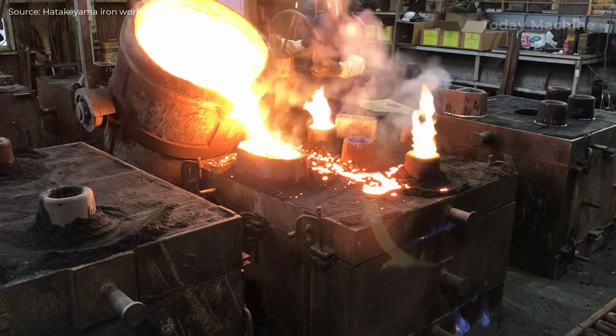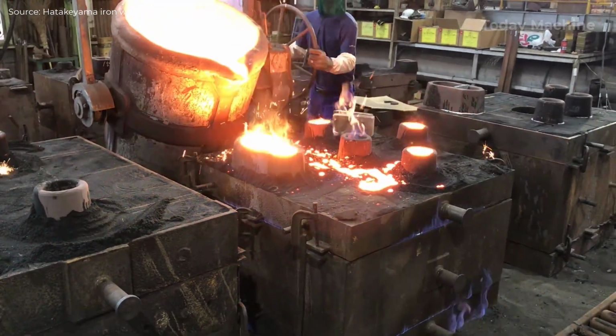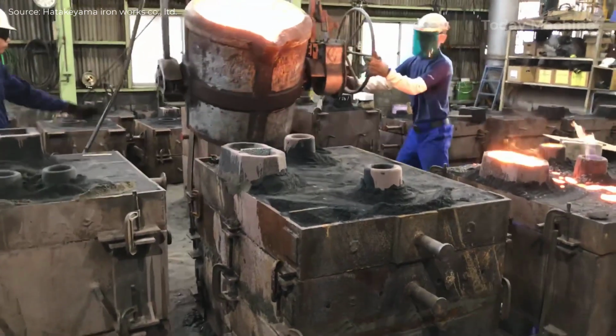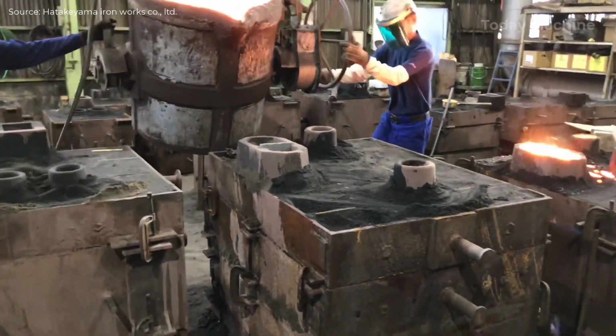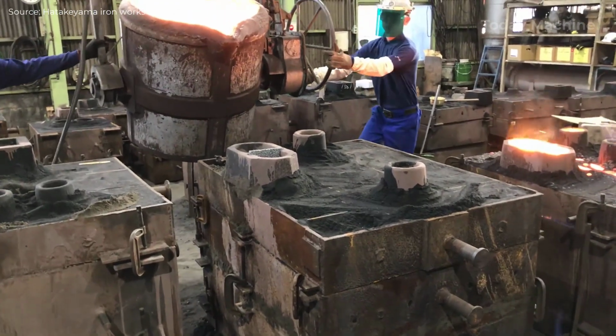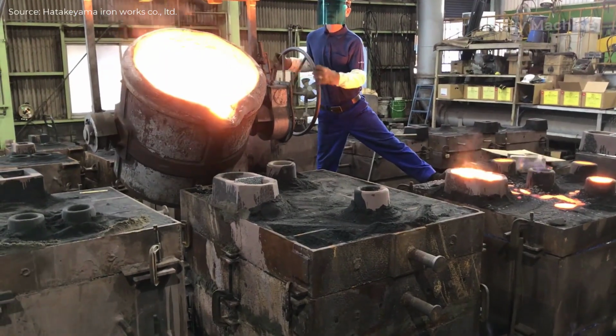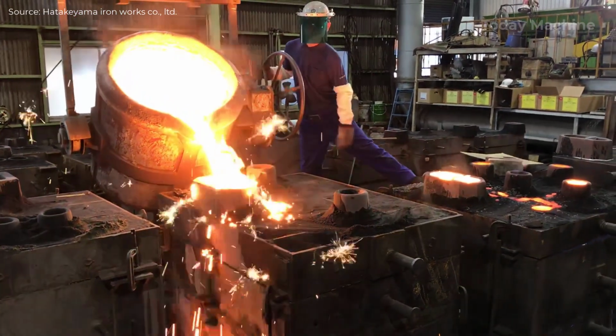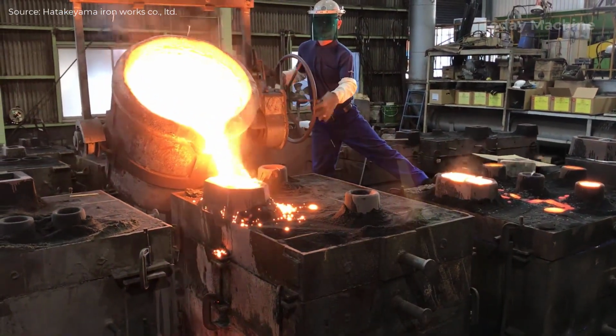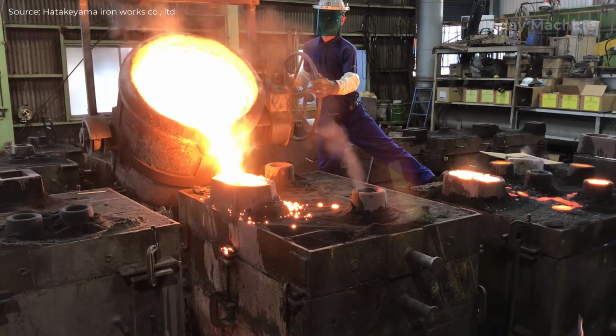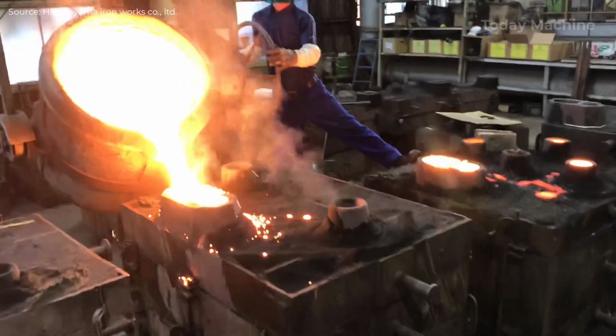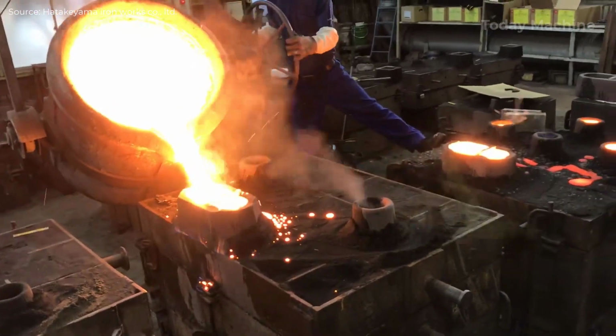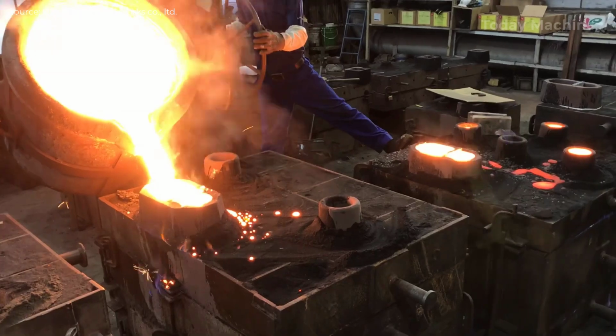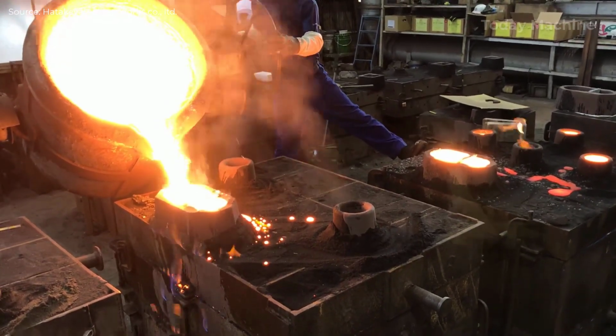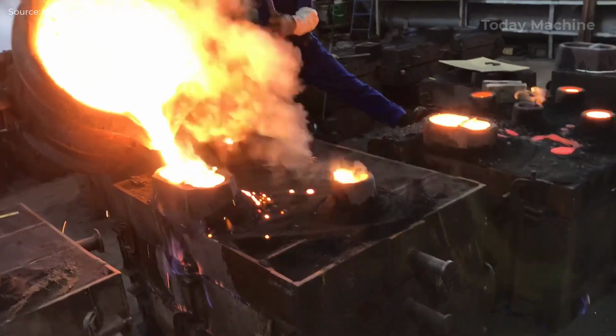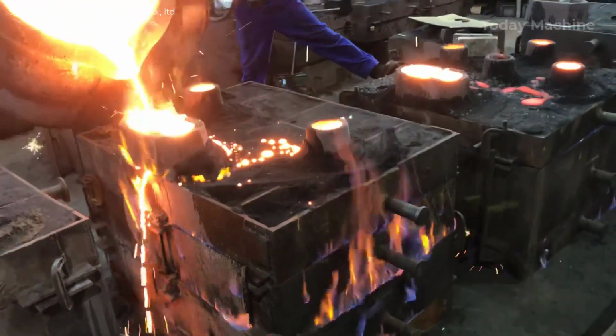Once the metal reaches the desired temperature, it is carefully transported to the cast iron molds, typically using a ladle. The ladle must have sufficient capacity, such as a 500 kilograms or 1000 kilograms capacity, depending on the casting size. The pouring temperature is crucial. For cast iron, it ranges between 1150 degrees Celsius and 1250 degrees Celsius. A controlled pouring rate ensures the mold is filled evenly, minimizing turbulence that could lead to defects like air pockets or inclusions. This can take anywhere from 30 seconds to a few minutes for larger castings.